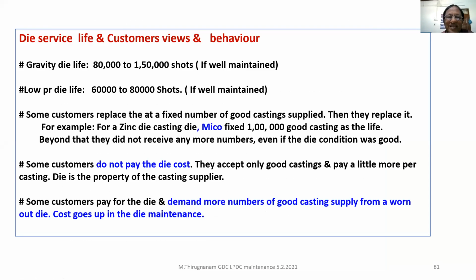When do you want to replace your die? Very important thing. The gravity die, if it is well maintained, you can go without any weight increase, 80,000 to 1 lakh. Even I have seen dies running after 1,50,000 shots. For low pressure dies, normally 60,000 to 80,000 shots if it is well maintained. Some customers replace the dies. I was supplying some castings to Mico. They fix the die life at 1 lakh for a zinc die casting. Even if the die is in good condition, Mico will not take even one casting after 1 lakh.